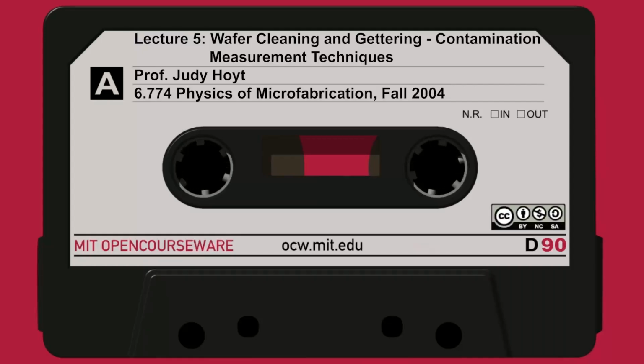So that's good. We can sample the top 10 angstroms, but notice that, like Heisenberg, in doing the measurement, I disturbed the crystal. I shot a bunch of ions in here, and now they're down here at 100 angstroms deeper, and they knocked things around in the substrate. So whatever atoms were down there, they disturbed them, they moved them around. They might have knocked them in deeper.